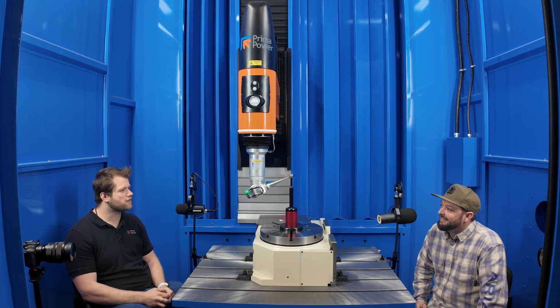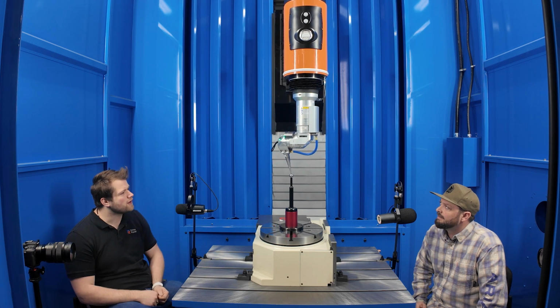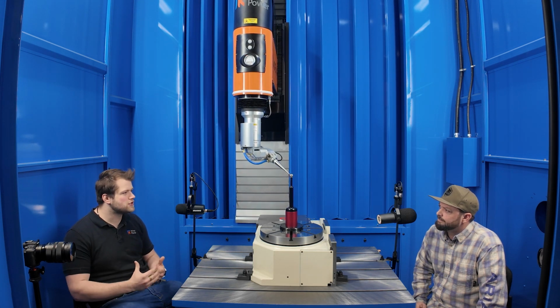What are some of the projects you've used that high power on? Yeah, so one of our latest ones is Project Vulcan. This was specifically developed to compete with E-beam. Not that kind of Vulcan, right? Not that kind of Vulcan, no. Vulcan is the Roman god of the furnace. And so this is made to compete with the E-beam, a 10,000 watt laser. Right now, anything above 6,000 watts CW is usually done on a robot. We decided to do it with a 3-axis system. More in our case, we've got 5. This is meant for nice and stable welds. You don't have any kind of vibration coming into your melt pool.